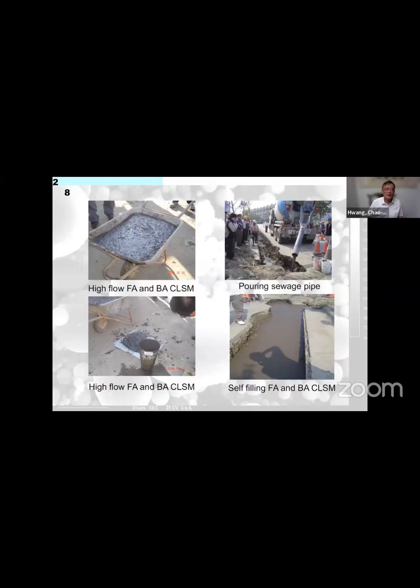So this is high flowing fly ash and bottom ash controlled low strength material. In Taiwan now, we have a label as a green material because it saves at least 50 to 60% of cement. So concrete like this one, flowing like this, can fill the sewage pipe. And this is a very common use in Taiwan. Next, please.